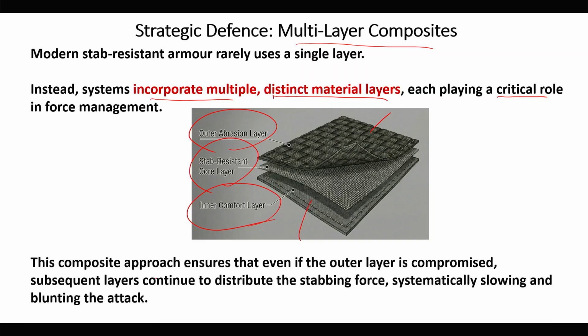So, this composite approach ensures that even if the outer layer is compromised, the subsequent layer will continue absorbing the load by distribution. It distributes the stabbing force and systematically slows down the stabbing through a blunting action. When there is a penetration, each layer will perform its own action, gradually the force will be reduced and the energy absorbed, and there will also be blunting of the knife. Then it will gradually slow down and the stabbing process will be restricted.